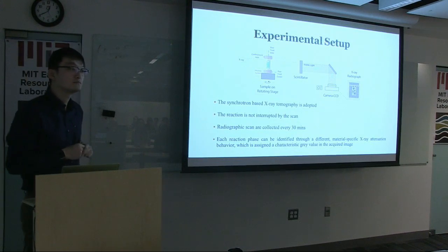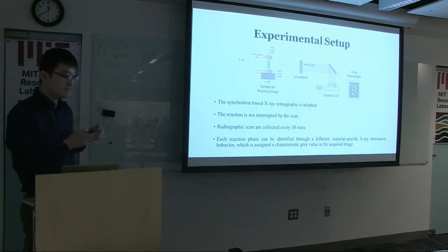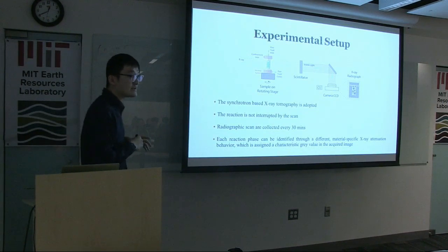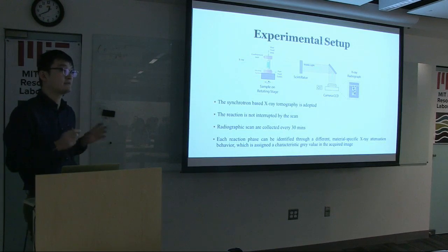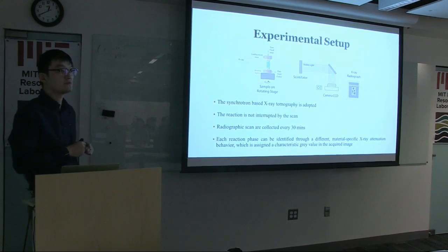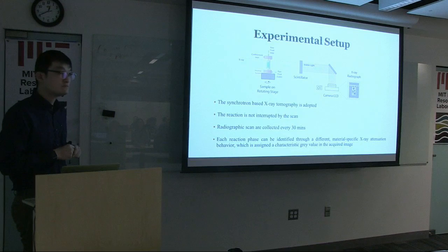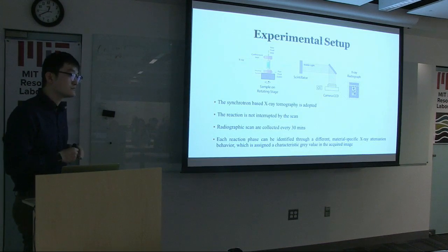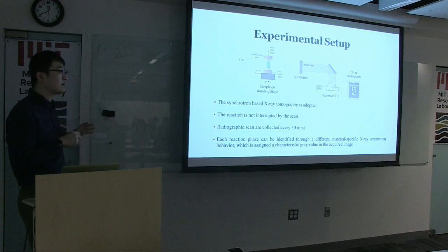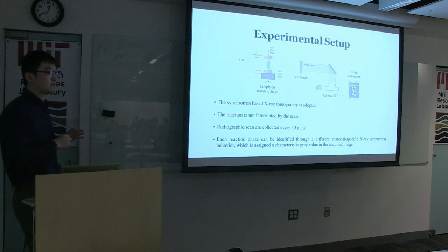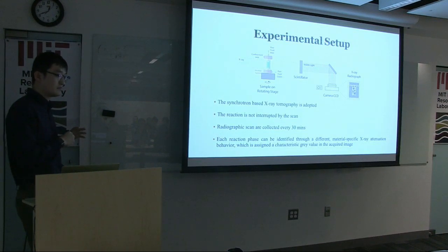And do you have pH in the system solution? We do not, because those fluids were reacted at 200 degrees Celsius. And when we take it out, the temperature also changed, so you can never really get the specific pH at that reaction condition. But your fluid's some kind of initial mixture of H2O and carbonic acid or something? Yeah, but we use sodium bicarbonate as a buffer. So basically, the solution is a sodium bicarbonate saturated solution. It's saturated with sodium bicarbonate? Yep. Okay.